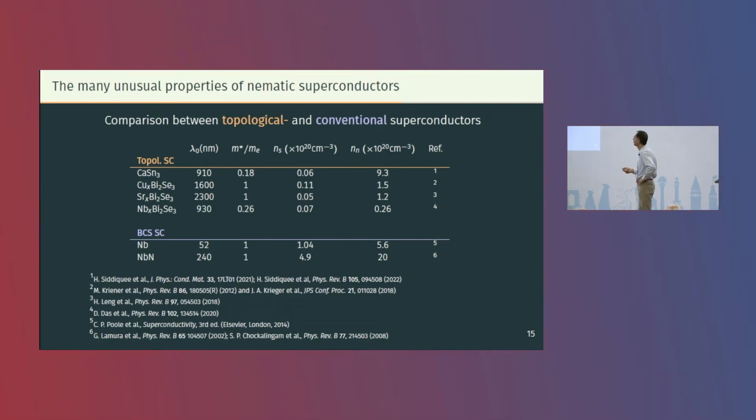Anyway, what I wanted to tell here is that what we found here looks already a bit unusual, anomalous, but it's not the case, because if you put these together with the other materials, which also have been studied by mu-SR, here we find these, let's say, huge numbers. By the way, we know also from Hc2 what is xi in this case, and we get a kappa of 60 for this material. The others also have very high values. So what is unusual here are these numbers, compared to the standard ones like niobium.